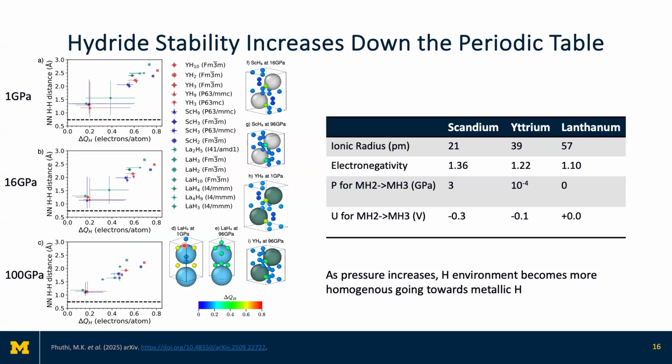And by the way, you consider only the average crystal lattices, whereas real local lattices can be quite different, as can be seen from studies such as pair distribution function or reverse Monte Carlo modeling. So the average structure maybe isn't the best structure to consider, because the variation in the real structure is big when we think about positions of ions in the crystal lattice.